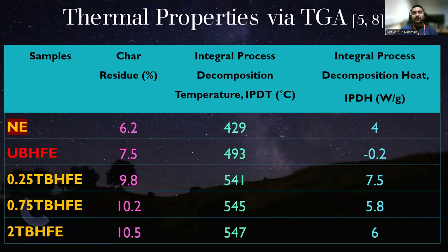That's again because of the presence of hemicellulose, it still has, what I should say, a higher heat capacity tendency. Although all the treated fiber reinforced epoxies got higher char values, their IPDH values are positive. So this is a very good indication. This parameter is a good indication. If anyone doesn't have a DSC to figure out the heat capacity, from the TGA result he can estimate how the heat capacity of the material should be. I should mention that I use this dedicatedly for biofiber, not for any other fiber or material.